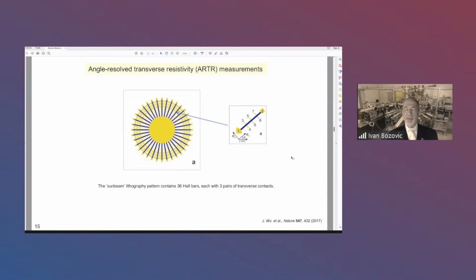It actually consists of 36 Hall bars. We run the probe current along the Hall bar, and then we can measure the longitudinal resistivity between, say, contacts 3 and 5 or 5 and 7, and the transverse resistivity between 3 and 4, 5 and 6, or 7 and 8. There are 36 Hall bars at 10 degrees from one to the next. Hence, we can measure the longitudinal resistivity at 72 pixels and the transverse resistivity at 108 pixels with the angular resolution of plus or minus 5 degrees.